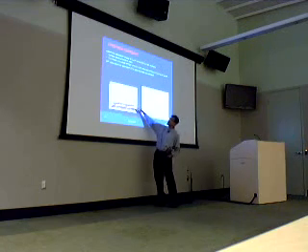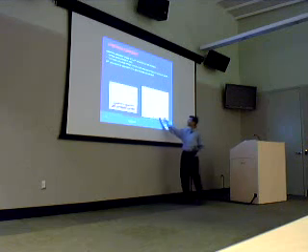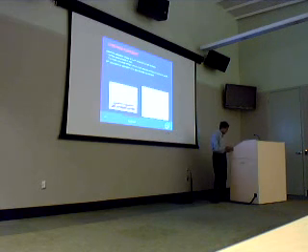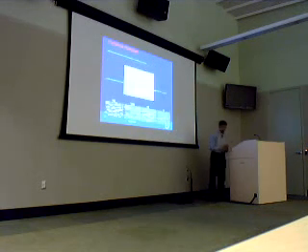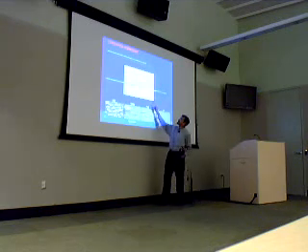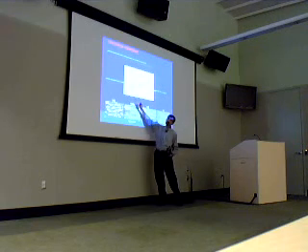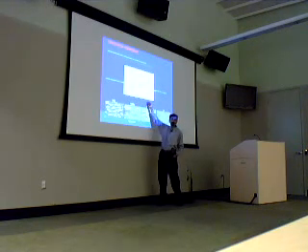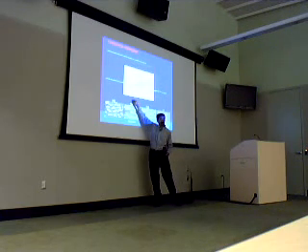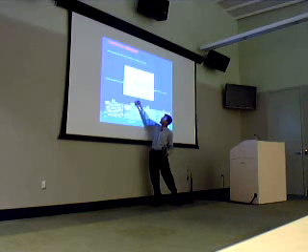What I show here is copper adhering onto the substrate, and this is the copper atoms. And we looked at both LDA and GGA, and you can see we minimized the energy and took the adhesion energy out of it. Very straightforward calculations. So what did we do with it? These were all the materials we looked at, the surface affinity going from the lowest on the left to the highest on the right. And so we predicted that you don't want tantalum, you would like to stay around this side.